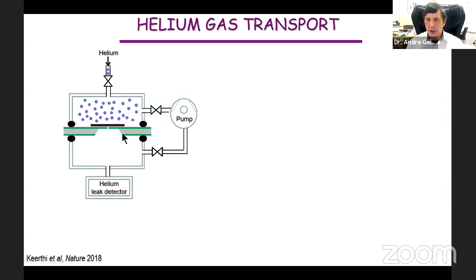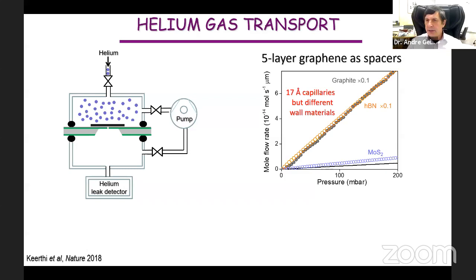And the very first result was already surprising. We have 17 angstrom capillaries using 5-layer graphene spacers. I think there were about 100 channels in parallel. And what we found is that the flow rate of helium very much depends on whether we use molybdenum disulfide as walls of the channel, or graphite or hBN as capillary walls. So notice the scale here. Molybdenum disulfide capillaries are 100 times less conductive with respect to helium than graphite or boron nitride channels.